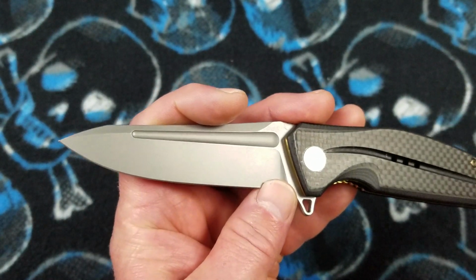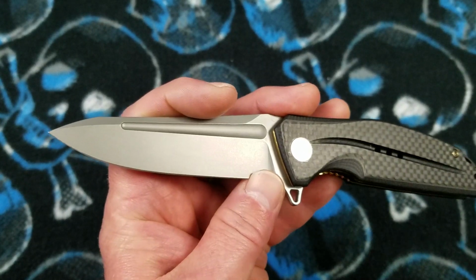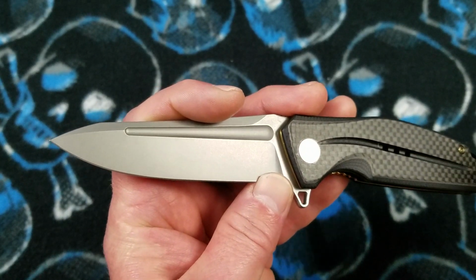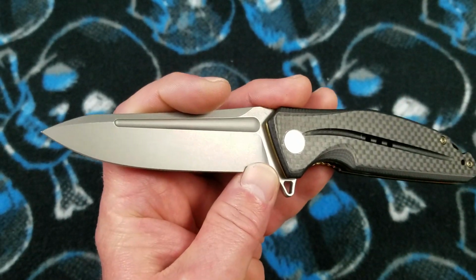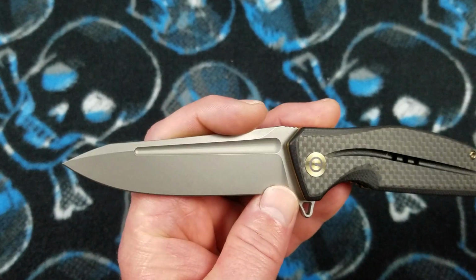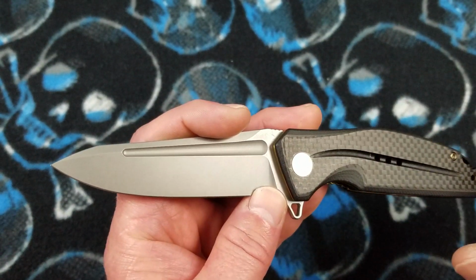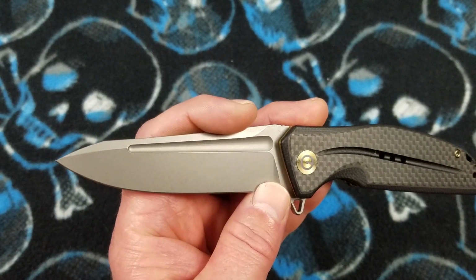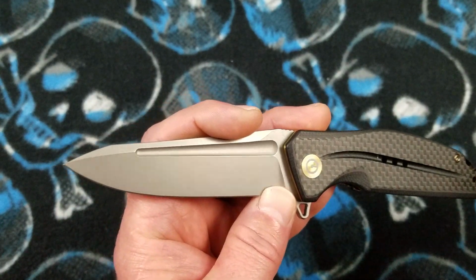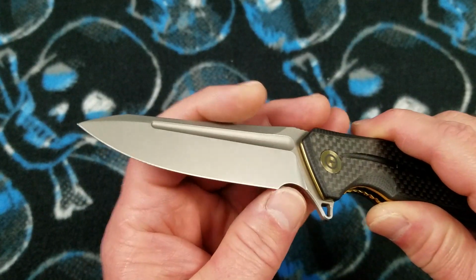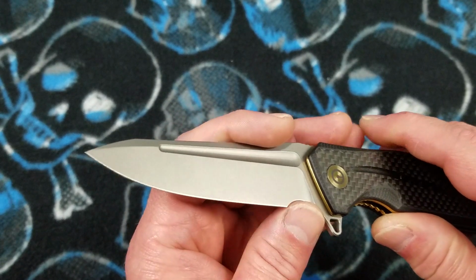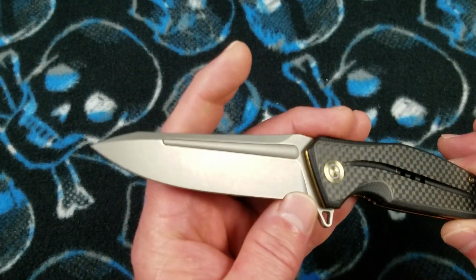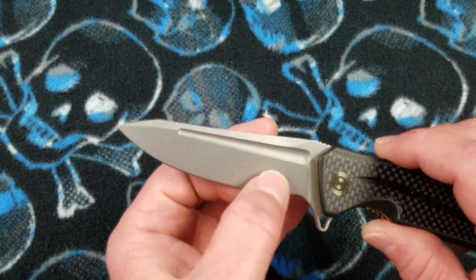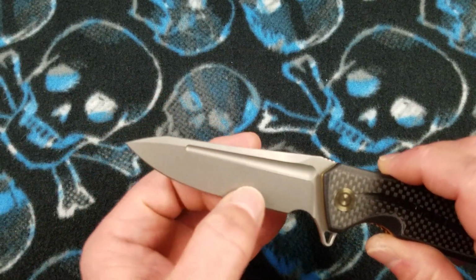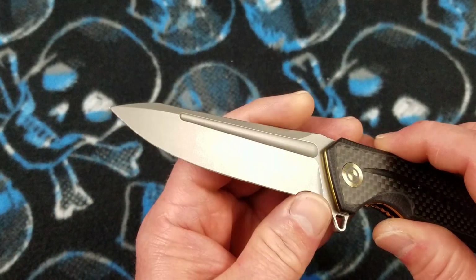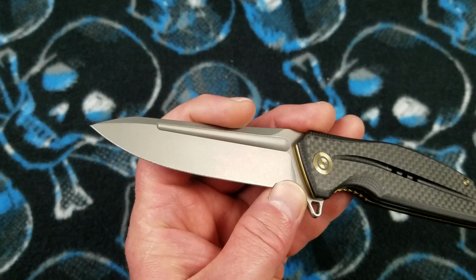It will hold a working edge. It's very toothy because of those big, large vanadium carbides suspended in the steel matrix. It'll hold a working edge for a long time. It's great for that. Toughness. Now, D2 can be a little chippy if it's too hard, if it's maybe run a little hot when they sharpen at the factory. If the edge grind is too thin, it's not the best steel for impact resistance. Now, it's not bad. Okay, with this 18 thousandths behind the edge, you know what? That is getting to the thin point, in my opinion, for D2, in my experience.